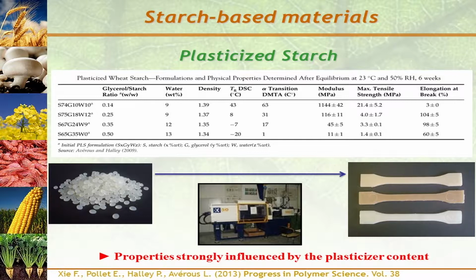So depending on the amount of non-volatile plasticizer, glycerol, the properties will strongly vary. Here you have wheat starch with different content in glycerol as plasticizer, 14, 25, 35, and up to 50% compared to starch. And you can see that the Tg varies a lot, and also the mechanical properties. With 14% of glycerol, you have quite high modulus, but very low elongation at break, very brittle materials. And if you increase the amount of glycerol, of course you decrease the modulus and increase the elongation at break, with the best compromise for this system being around 25% of glycerol, for which you keep quite interesting modulus, but with the highest elongation at break.